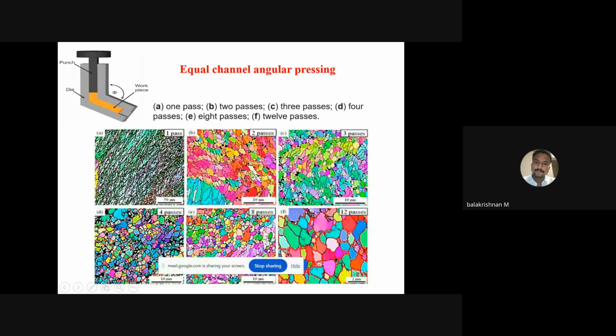But in this case, we can observe that 8 passes have finer refinement compared to other numbers of passes. So in this case, the 8-pass equal channel angular process will provide better results compared to the 12-pass process.